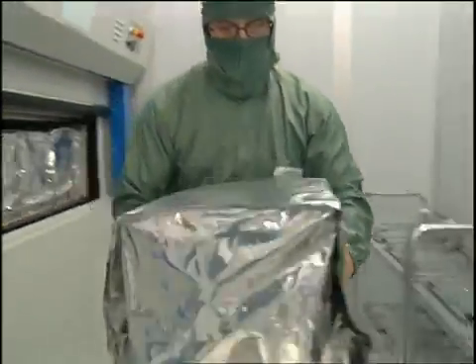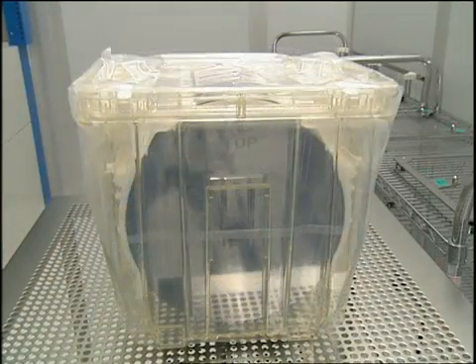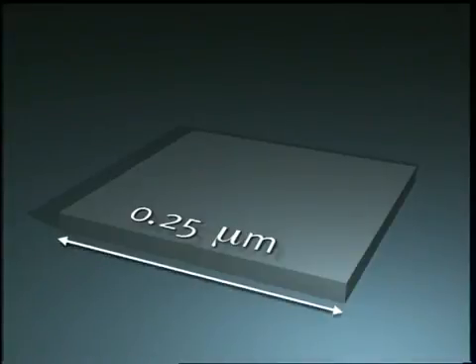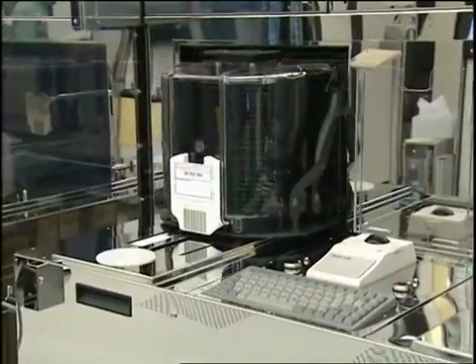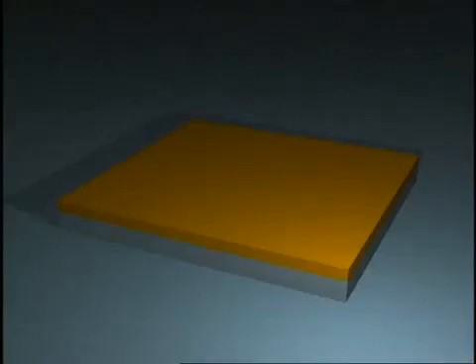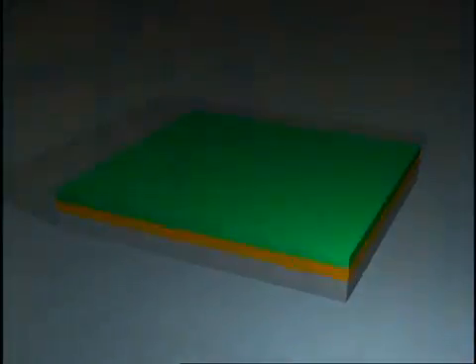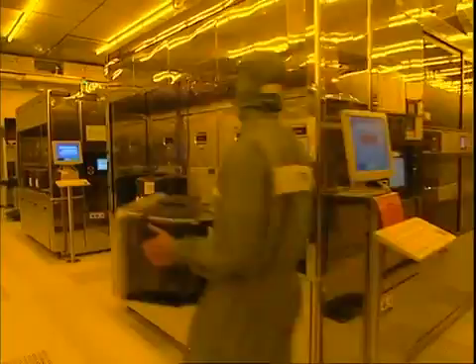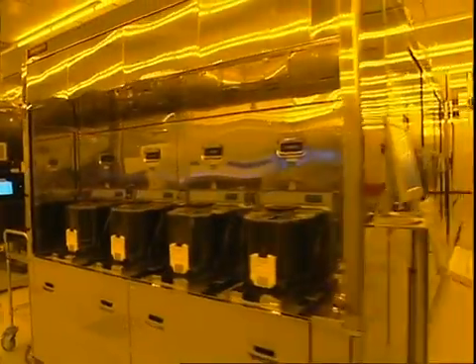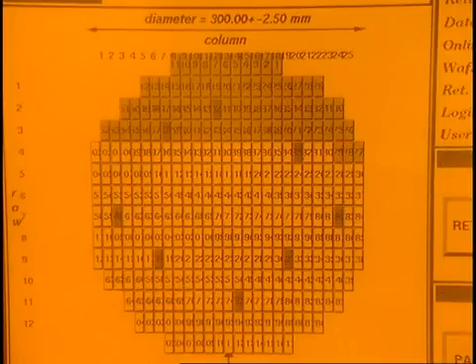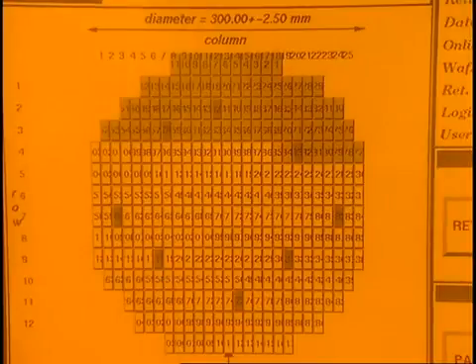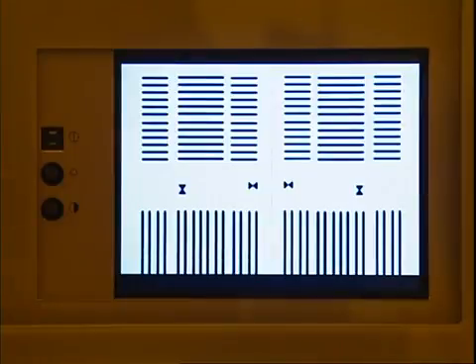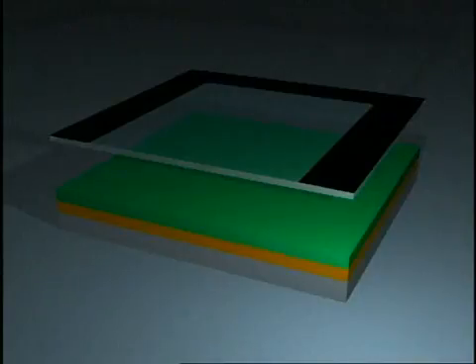The basic material for the chips is a 1-millimeter thick silicon wafer. First, the conductive or non-conductive layers are produced by oxidation of the surface at approximately 1,000 degrees Celsius in a high-temperature furnace. A drop of photoresist is uniformly distributed by centrifugal force on the oxide layer produced, thus creating a light-sensitive layer. Special exposure machines — so-called wafer steppers — transfer the masks by exposure to the silicon wafer. The accuracy of adjustment to the features already produced must remain within a tolerance of one one-hundredth of a micrometer. Next, the photoresist-coated wafer is exposed through a mask.